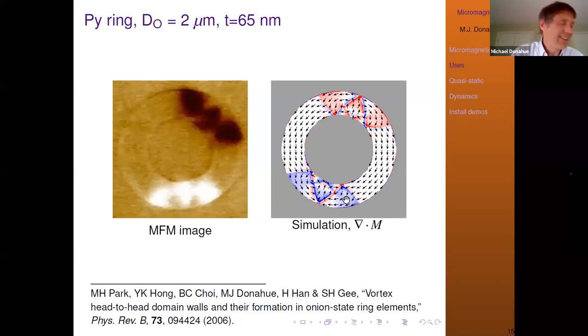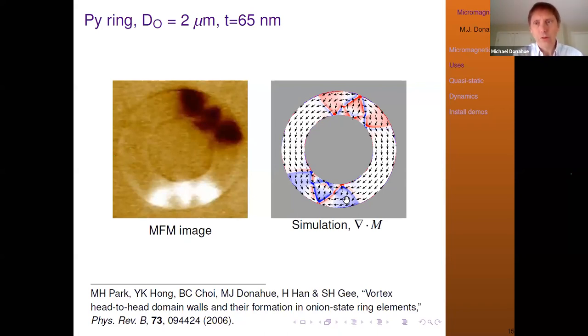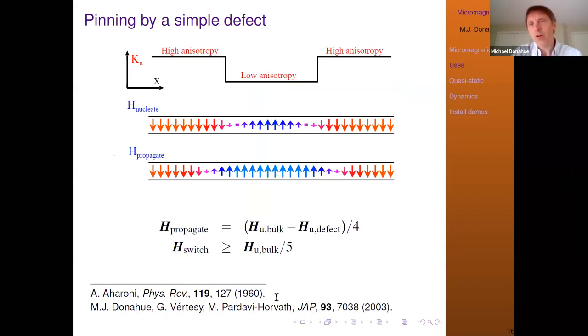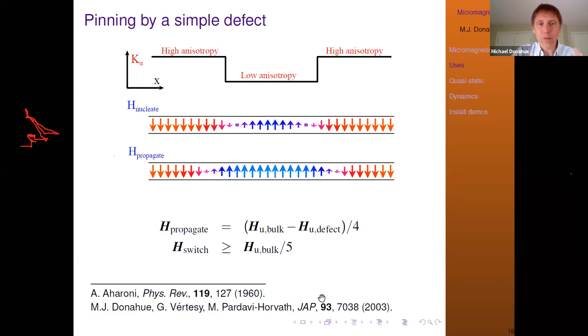A question: can the simulation include DMI? Yes, there's already an extension written by André Thiaville and collaborators at Orsay; it's included in the latest release of OOMMF. You can also model the effect of defects — for example, modeling a defect as a change in anisotropy to see what effect it has when you try to move a domain wall past it. I extended some analytic work done by Aharoni in the 1960s, going from his 1D analytic approach to a 2D film simulation introducing defects.